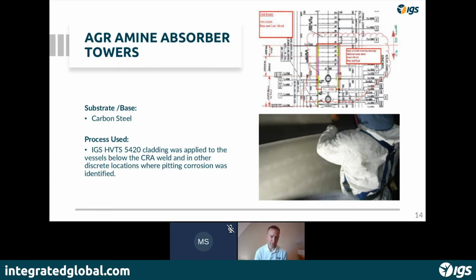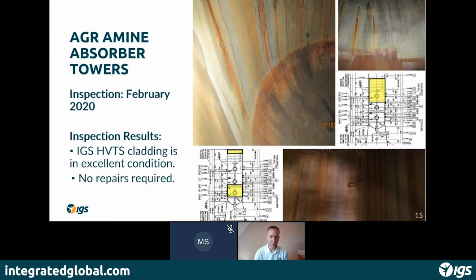So we'll do follow-up inspections with the client, and we'll go through with the client any requirements that there might be for expansion or changes to the system that they're using. So with this client in 2011, we applied the IGS 5420 system, which is the standard system we're using, as I said before, a Hastelloy-based alloy for these environments. We went back in 2016 after 5 years in service, and then we were back again just in February this year in 2020. We did the inspections, and we found, as we expected, that there was no degradation of the